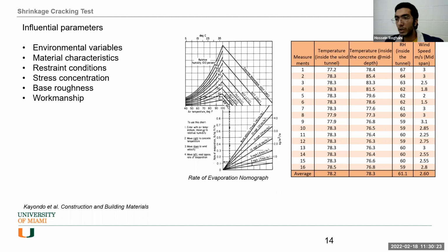And in terms of restraint conditions, as I told you before, what actually causes the shrinkage cracking is the restraint, which doesn't let the concrete shrink by the same amount at all points in the depth and in the length of the concrete. If the entire slab shrinks together, there will be no cracks. With restraining, you will cause the stresses to exceed the concrete tensile strength and make the cracks. And also we have something we call the stress concentration. I think all of you are familiar with that.